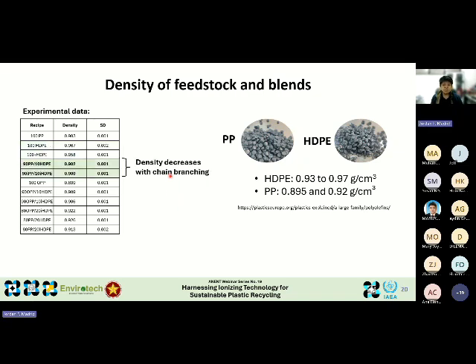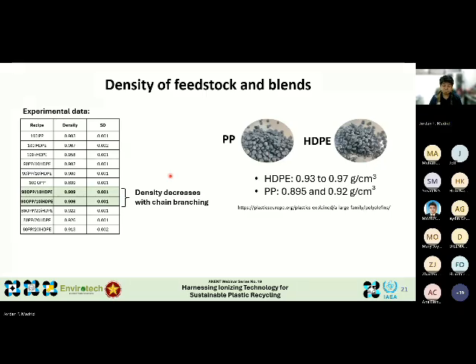The same was observed with the blends, like for the 90:10 polypropylene-HDPE blend, where the use of irradiated HDPE contributed to the lowering of the density. Even when we used OPP, the plastic waste sourced from Envirotech, we observed the same trend: the incorporation of irradiated HDPE still led to a reduction in density, showing that this effect is consistent whether we start with recycled materials or with unprocessed plastic waste feedstock.